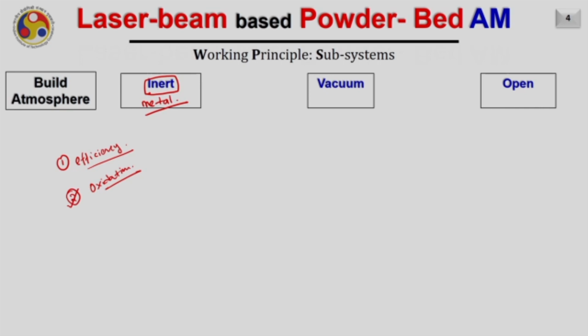As these spherical particles are very tiny in size, the surface area is quite high. Therefore, immediately when they come into contact with the open environment, there is a possibility that the powder gets oxidized, and if the powder particles are subjected to preheating, the chances of oxidation will be too high. Therefore, to avoid that, the entire environment is usually purged with an inert gas such as nitrogen or argon. In some machines, CO2 is also used to create the inert environment.